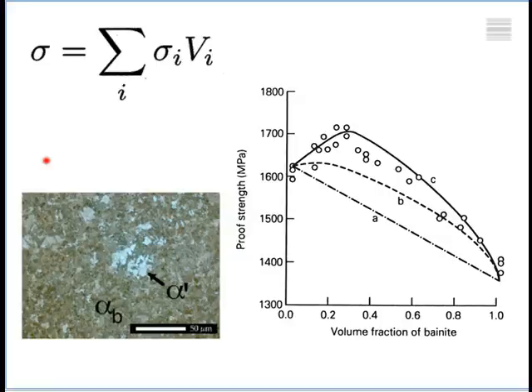So when we come to mixtures of microstructures, we have to think a little bit more about how those mixtures interact with each other. So for example, if I make a composite of glass fiber in plastic, when I pull the composite, the plastic will deform first until it gets to a point where you can transfer stress onto the glass fiber. And similarly here, the martensite is hard, the bainite is not. So first, the bainite has to deform and transfer stress onto the martensite.